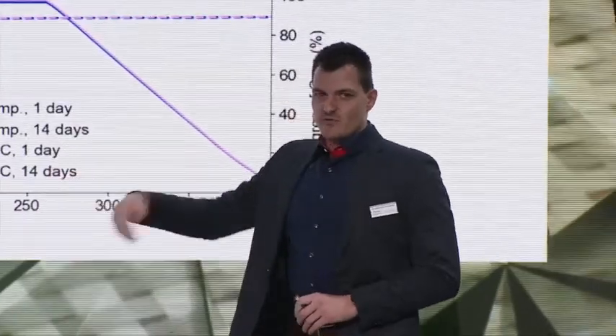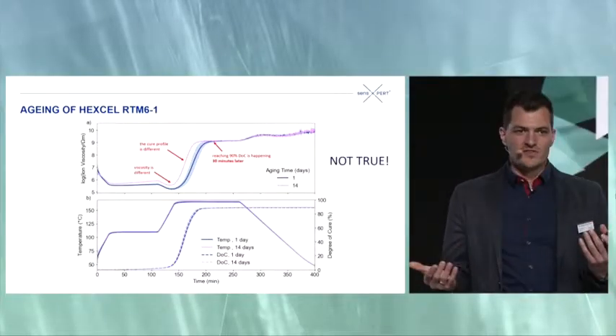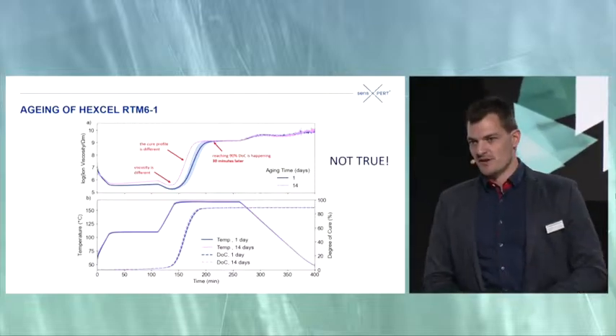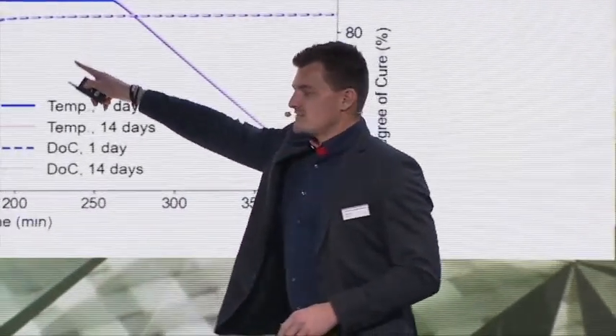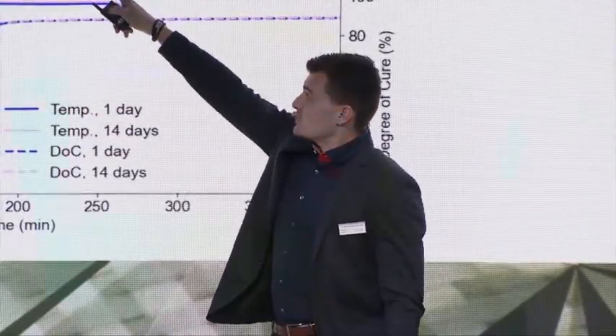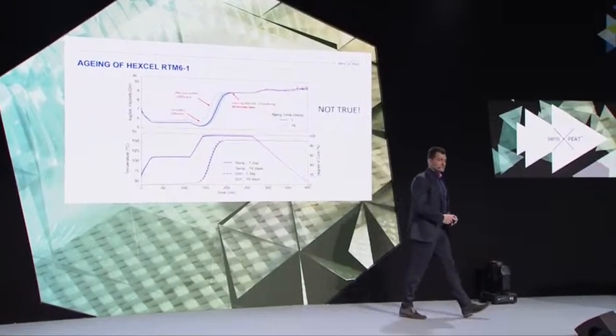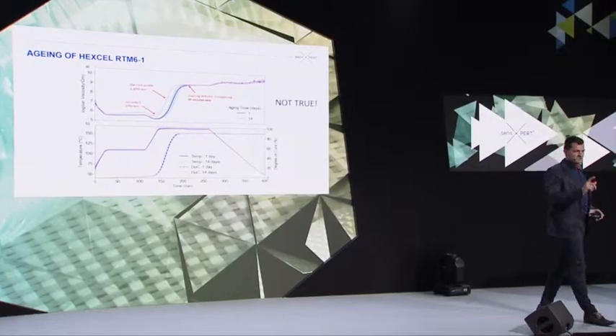Hexcel RTM6-1, the reference is a laboratory measurement, one batch of material. We create the reaction kinetic model that just uses as input data the temperature in the manufacturing environment. But if the material deviates, we cannot take that into account with state-of-the-art technologies. This is why reaction kinetic would say the same behavior, but what you can see in the upper picture is the deviation that really happens. Yes, the mechanical performance at the end is the same, but the behavior during production is totally different.